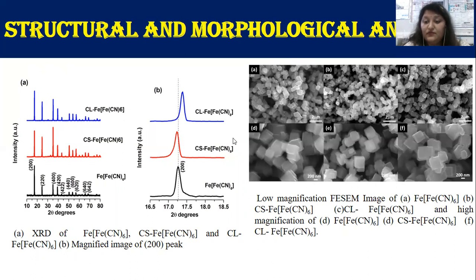Figure 2 displays the low magnification and high magnification field emission scanning electron microscopic images, and the particle size of the samples was uniform, about 500 to 600 nanometers. From the micrograph, it is evident that the morphology of the samples is well-ordered cuboids. It is revealed that the chemical sodiation didn't invoke any significant change in the particle morphology, while a notable size decrease of cuboids is observed for the lithiated sample, and it may be noted that lattice contraction was also observed